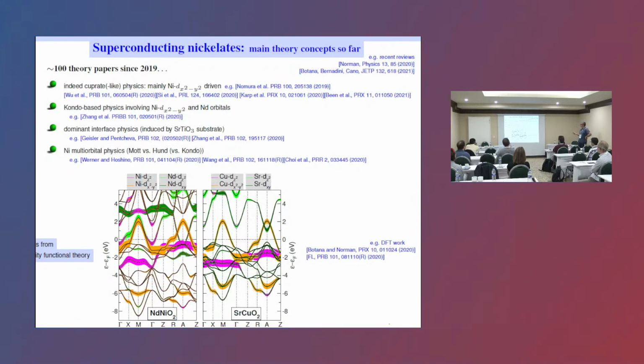There are not too many people in this group, but it might still have some relevance. We have to see. Then there was, early on, the idea that it could be an oxide heterostructure effect, but that has been ruled out quite recently because there's not a 2DEG formed at the interface, but rather a reconstruction to resolve the polar issue that comes from the nickelate. And then, of course, there's a large group that claims that there's multi-orbital physics. Many people are in this group, and I'm also in this group.